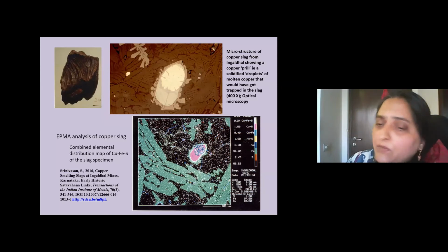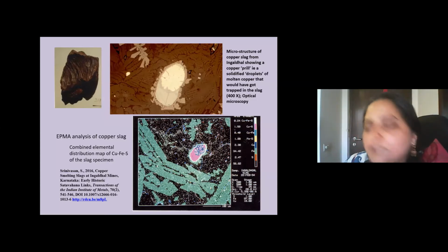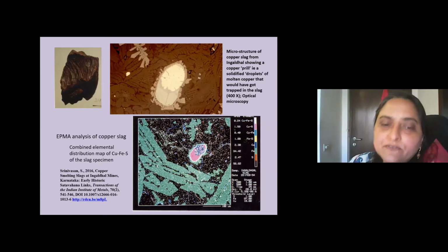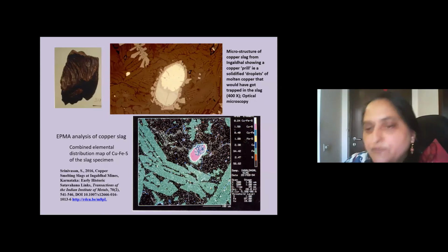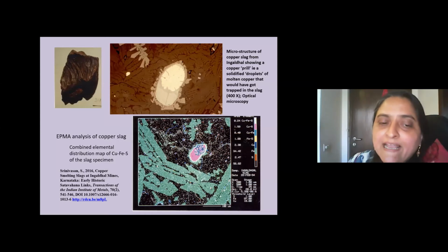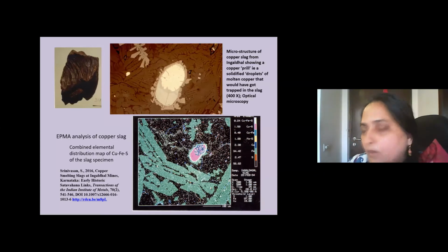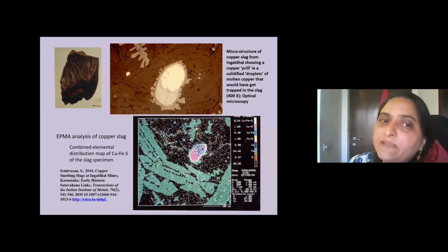And now we also have these techniques. It's gone from just optical microscopy to electron probe microanalysis, which has become a very useful technique here, where you use wavelength dispersive spectroscopic analysis. And there is also this technique where you can actually see the distribution of the elements. In this case, this is an elemental distribution map for copper, iron, and sulfur. And you can see very clearly how the copper is segregating into the smelted metal, and then it has that sulfide ring around it. And then you also see this lath-like fayalite structure. So that gives us various methods of reconstructing the traditional processes, or the archaeological record.